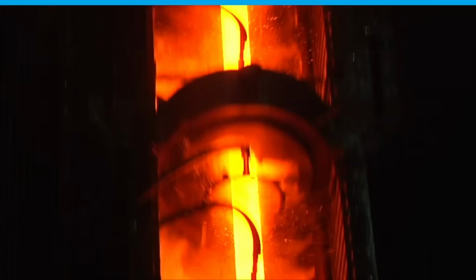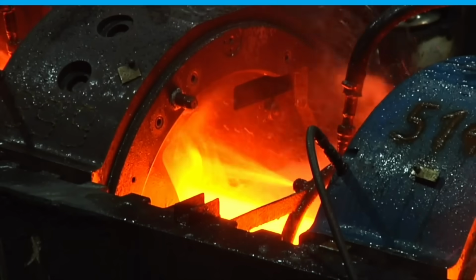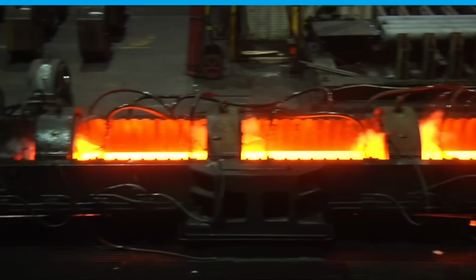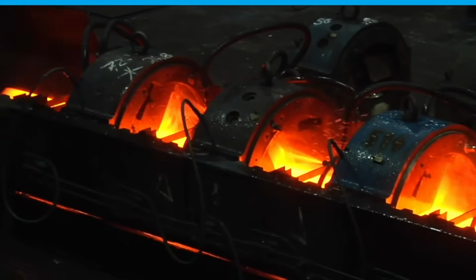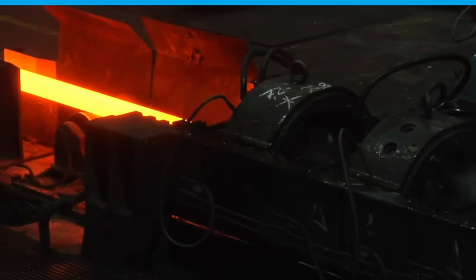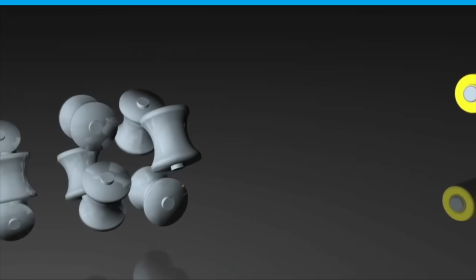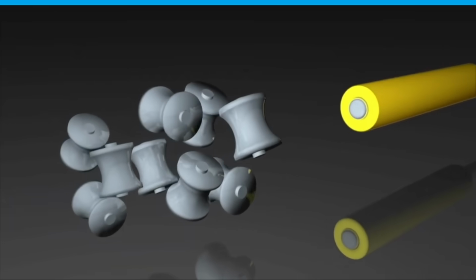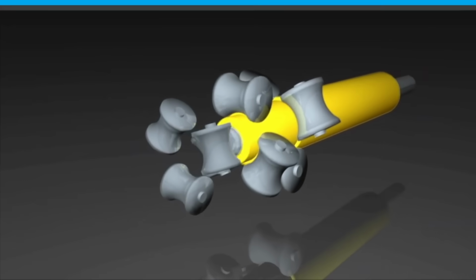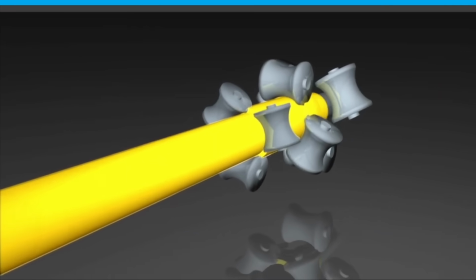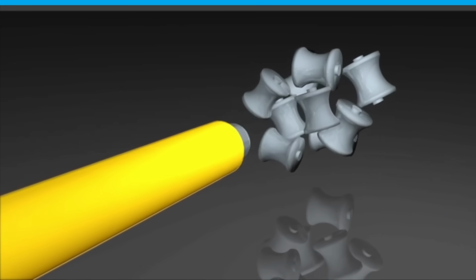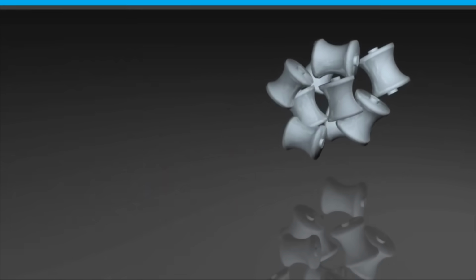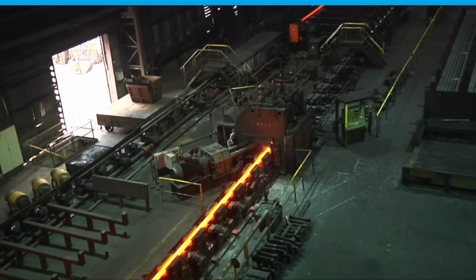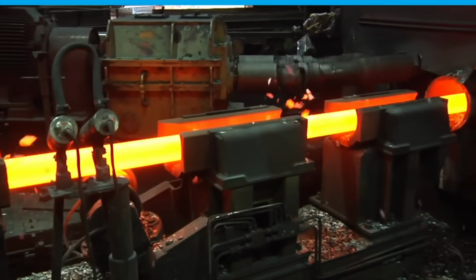The hollow shell then moves to the elongation mill, and the workpiece's greatest deformation occurs to achieve the desired diameter and wall thickness. At this point, a driven mandrel rod as an internal tool pushes the hollow shell through up to 16 rollers. The hollow shell is elongated up to 20 times longer than the starting material at the start of the process. The tool and workpiece are separated from each other by a release rolling mill.